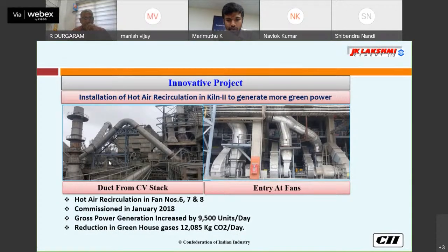This is one of the case studies from JK Lakshmi Cement. On the left side figure, we can see the recirculation duct from the stack, which is given to the middle fan of the clinker cooler. On the right side, the new fans are there. For hot air recirculation, out of 10 fans, for 6, 7, 8 we have given the hot air, and it was commissioned in January 2018. It has increased the output and given savings of around 9,500 units per day. It also helped reduce 12,000 kg of CO2 per day.